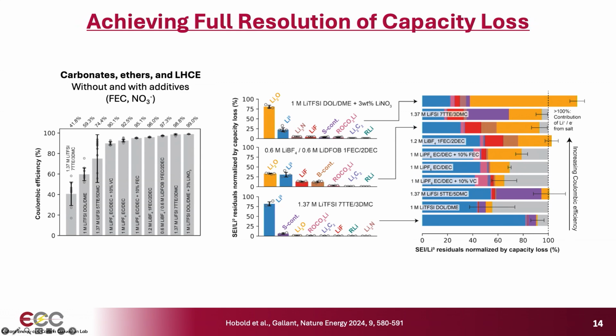So we chose a set of 10 diverse electrolytes spanning different electrolyte classes, looking at carbonates, ethers, some other high-performance systems, and looking at a range of Coulombic efficiencies. And we applied our capacity loss methods to them. Okay. So what you see here in the middle is an example of 3 of these, and you see the capacity loss broken down by rank. So you start to see the diversity emerging here. And then over here, we rank them all in order of lowest to highest Coulombic efficiency.